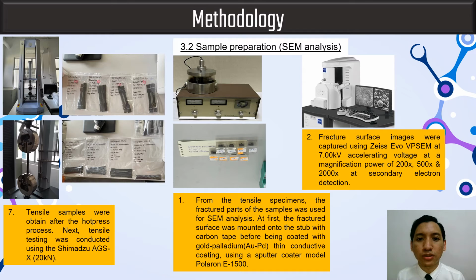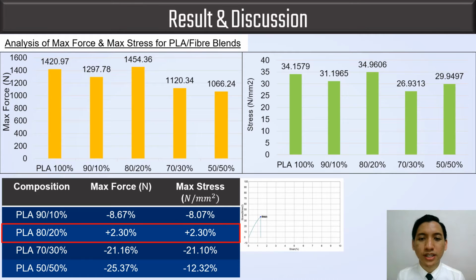So for the result and discussion, Table 1 shows the max force and max stress of the PLA fiber blend from the tensile strength test. Addition of fiber up to 50% into the PLA blend reduced the mechanical strength of the blend, except for 20% fiber.